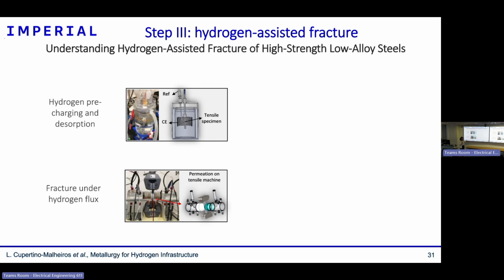So in all those tests, there are basically two big methodologies. One, you pre-charge your sample and then you do the test. The other one, you do the test inside of the environment. I think that reproduces better, depending on your application, of course. For some applications, it will better reproduce the conditions in the field. And in that case, hydrogen is entering while the test is being performed, and of course that will also change the absorption. Once you have a crack, you have stress fields. Here we discussed trapping, but hydrogen also accumulates at stress fields. So you also tend to accumulate more hydrogen once you have a crack, a defect.